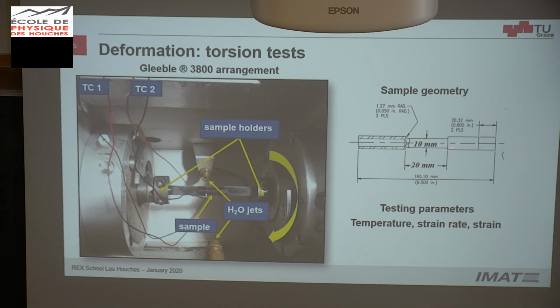And the most important thing is to decrease the gradient of temperature here. You don't want to have very large gradients of temperature, because this gradient then produces some flow localization, which is not desired. Yeah? So you have a technical question. Your sample has this total length, or is only 20? The total length is here. All of this is the same. And you drill a hole to slide the thermocouple in? No, the thermocouple is spot welded here on the shoulder of the sample.